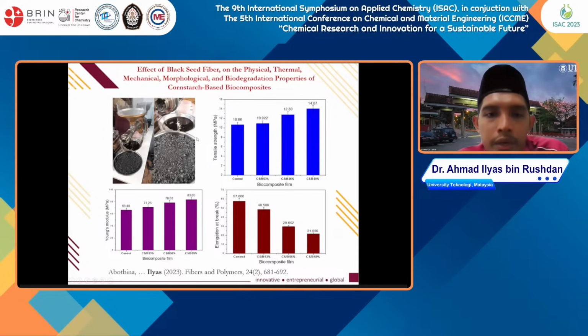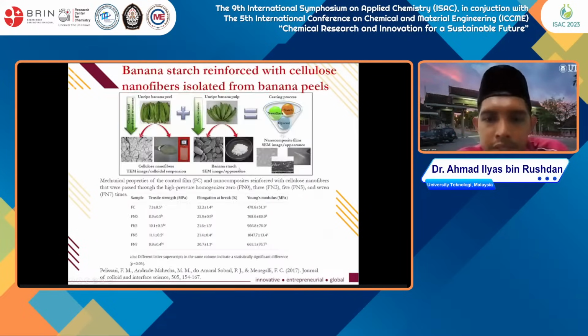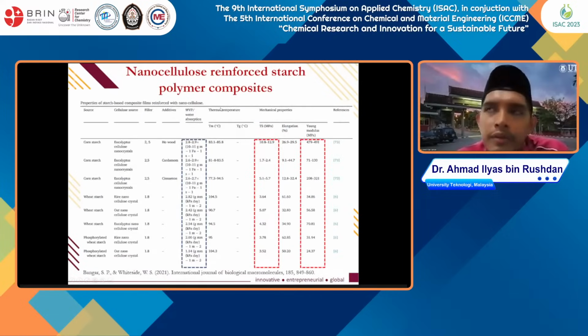This one uses Habatu Sauda reinforced with corn starch, and then we also have banana nanofiber reinforced with banana peel starch. We can see that the tensile strength increased up to 5%, and then decreased after 7%. So there's a various study here.